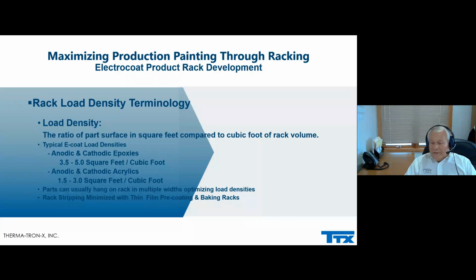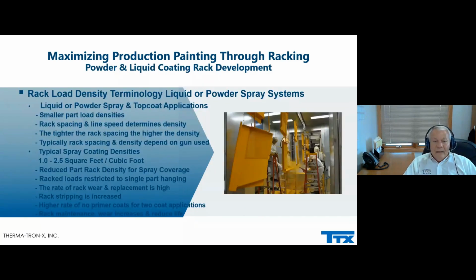or 0.1 to 0.2 mils, and you use hardened steel rack tips, you can break that surface and maintain ground for electrocoating. Some of the rack load densities that you see for liquid and powder applications are smaller load densities. Rack spacing and line speed determine the density, more so than the number of parts per rack, only because they could only be single hung. The tighter the rack spacing, the higher the density, obviously.